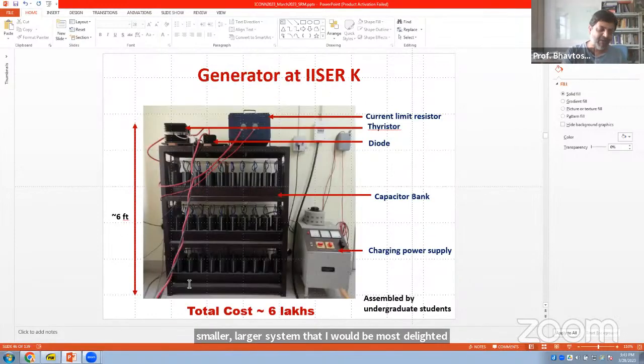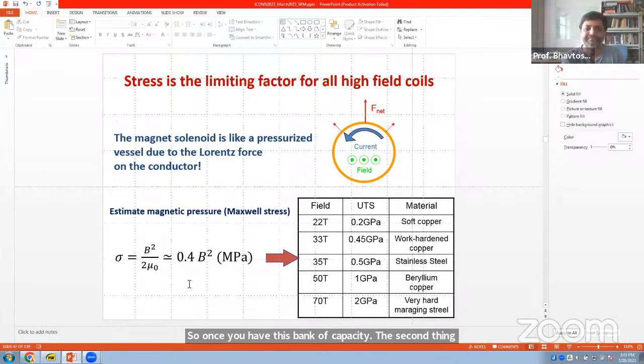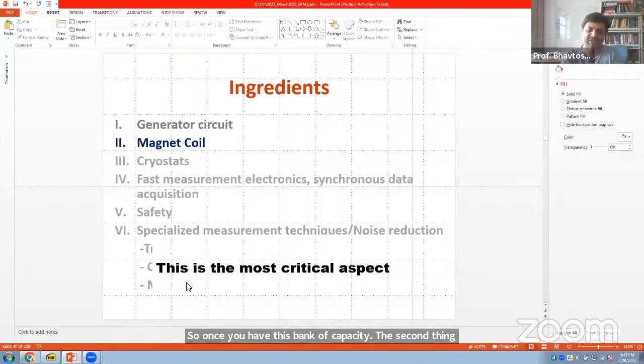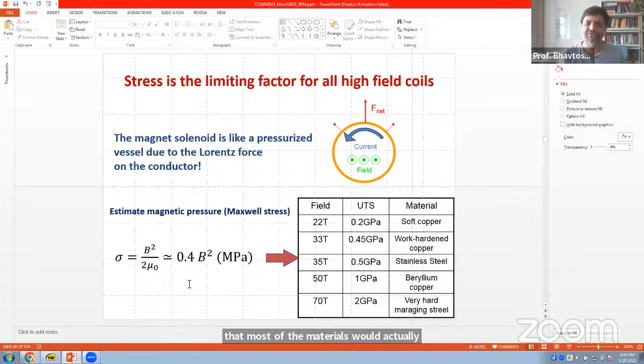Once you have this bank of capacitors, the second thing is the magnet coil. And here again, it's interesting because one of the problems is that beyond 20 Tesla, the stress in the material is so large that most of the materials would actually explode because of the Lorentz forces which they experience. So the coil generating a magnetic field is like a pressurized vessel. The only way to make a coil is to reinforce the material by some high strength fiber. For instance, if you just choose soft copper to wind the coil, then beyond around 22 Tesla, the pressure would be so large that the coil would explode.